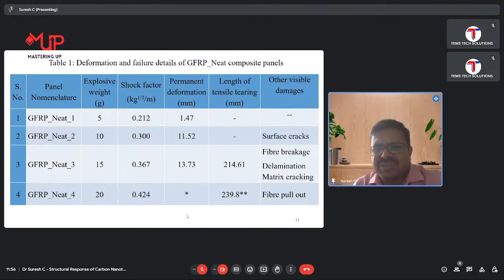Next, if any tearing has happened: for 5 gram there is no tearing, because the structure withstands that load, and for 10 gram also there is no tearing, but we observed some visual cracks on the surface of the structure. For 15 grams, there was a tearing on the edges. The length of the tearing we measured is 214.61 mm, and for 20 grams we have measured the tearing as 239.8 mm.